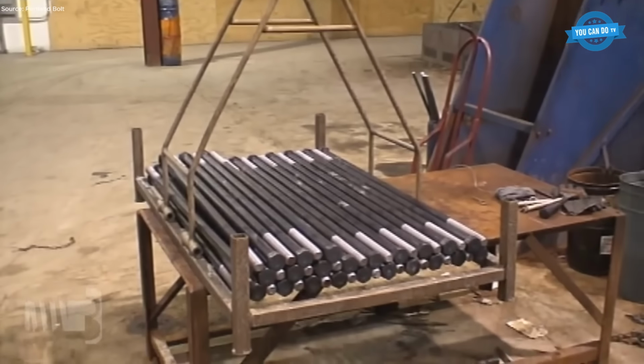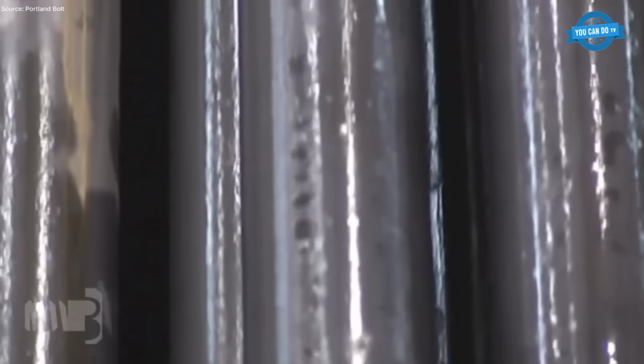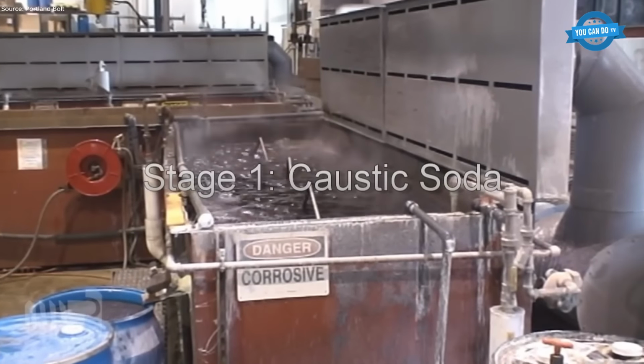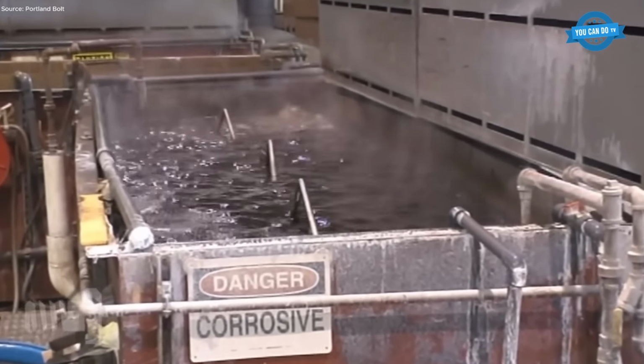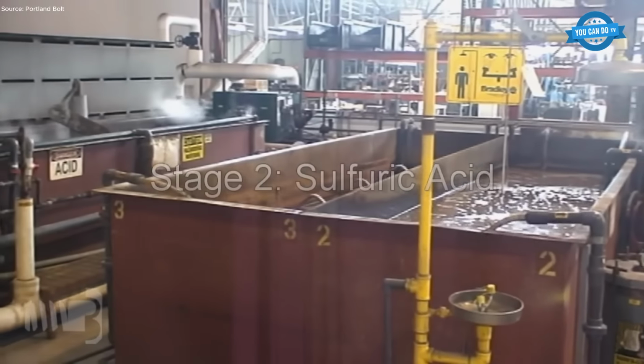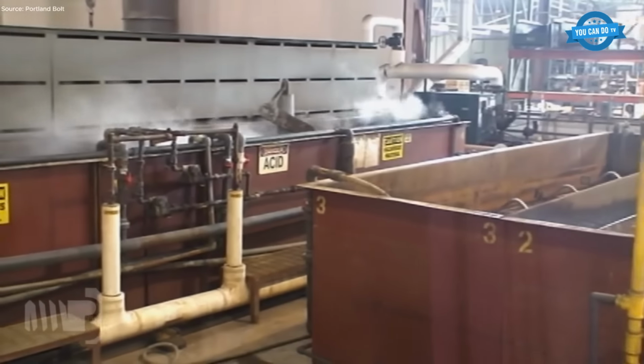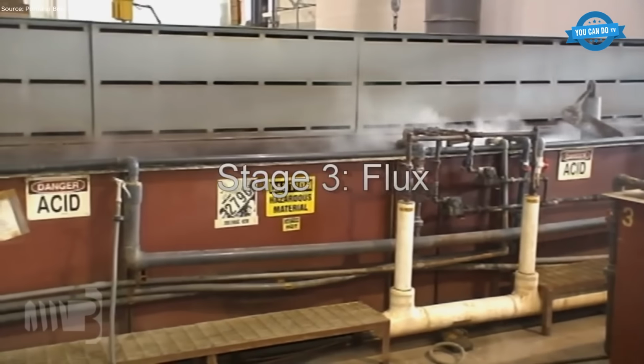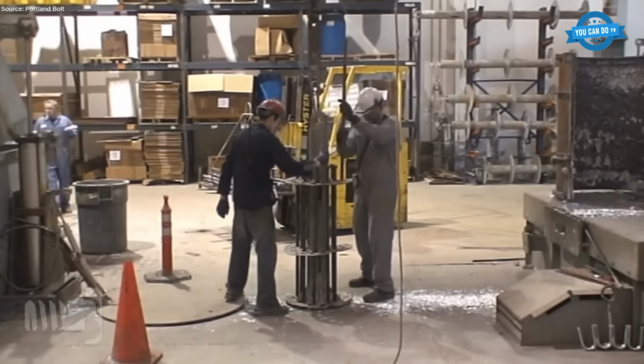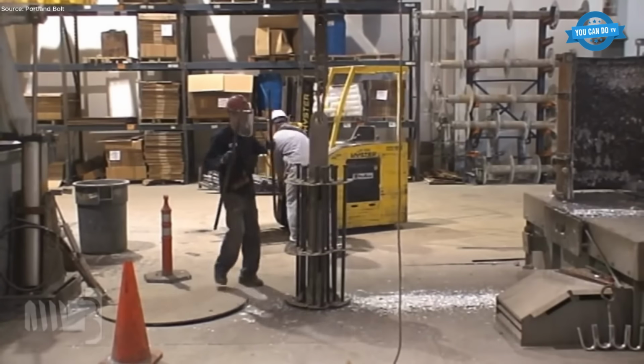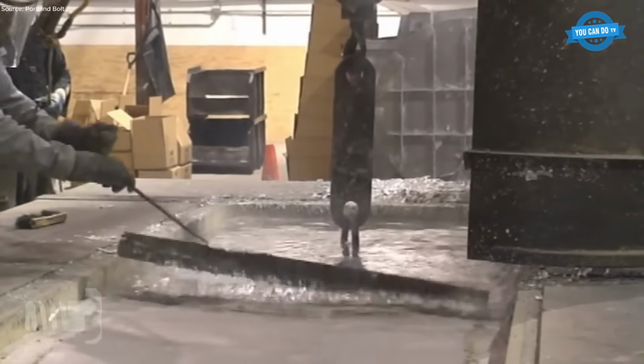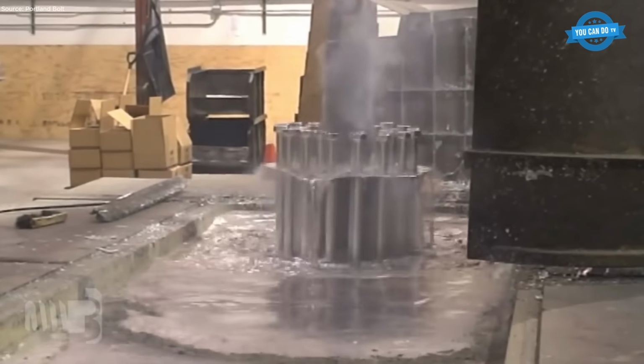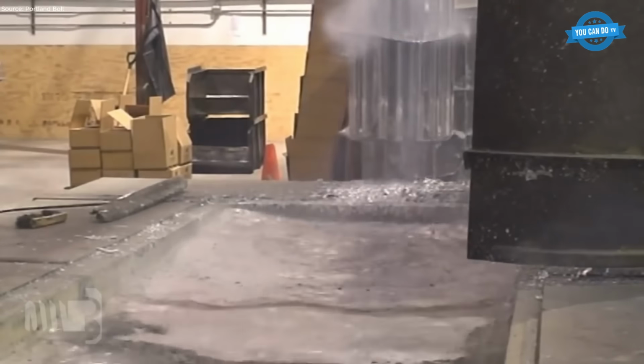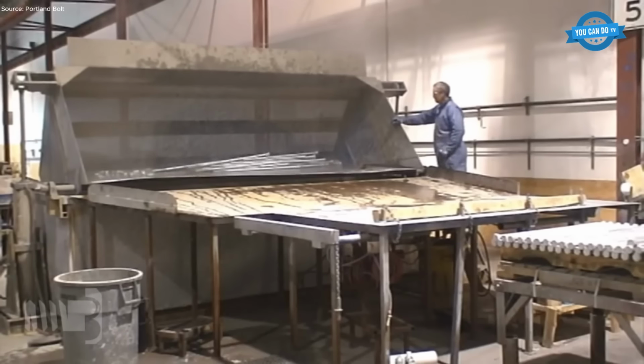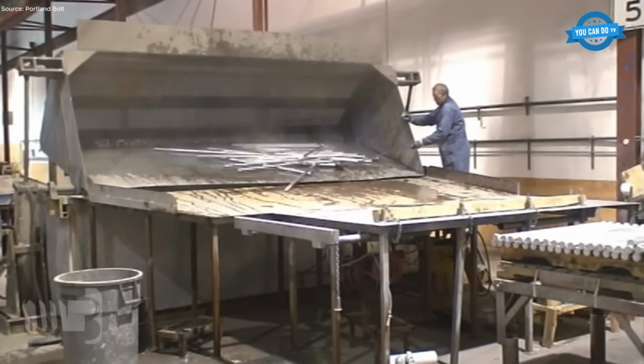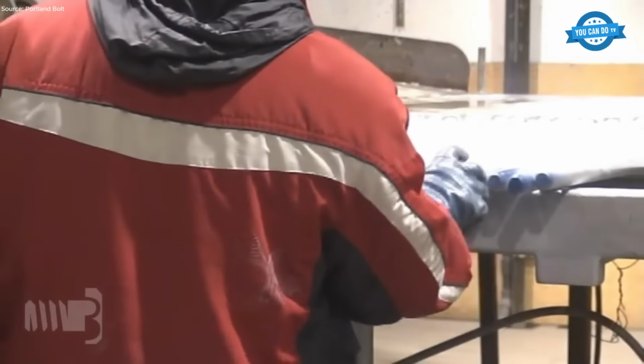Prior to galvanizing, bolts undergo pickling, including caustic cleaning, acid descaling, rinsing, and fluxing to prepare the surface. Hot dip galvanizing follows, immersing the bolts in 840 degrees Fahrenheit molten zinc. Excess zinc is removed by centrifuging, then bolts are quenched, inspected, marked with grade paint, palletized, and shipped with full certification documentation.